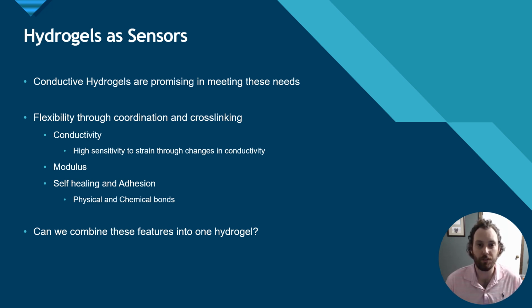Hydrogels bring with them the benefit of their tunability, whether by changes to physical or chemical bonding within the hydrogel, uses as additives or other materials to add properties that were not classically seen in hydrogels. Hydrogels really are one of the more tunable materials at our disposal. Things that we'd be interested in tuning in a possible strain sensor that could be accomplished through hydrogels would include conductivity through the introduction of conductive ions and other networks such as carbon nanotubes, adjusting the modulus through cross-linking, crystallization, or intramolecular forces. Another property that's not currently available to classical conductive materials would be self-healing and self-adhesion. These can be approached through the use of hydrogels.